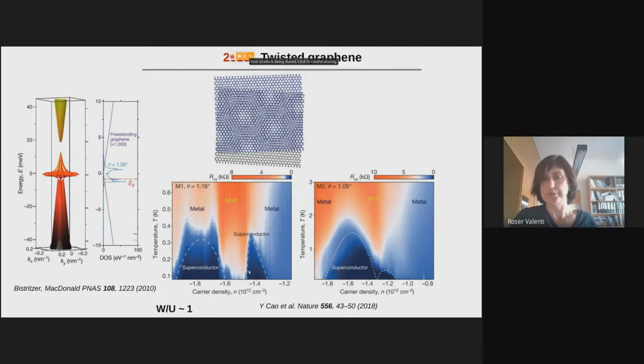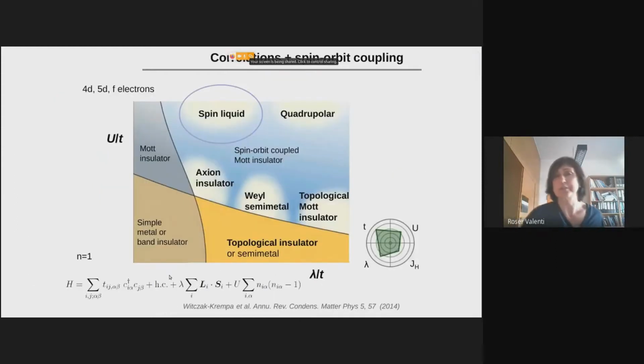So now let me bring the fourth interaction into the game, which is the spin-orbit coupling. And here, if we now include spin-orbit coupling and we consider systems where all these four interactions are playing a role, depending on the strength of the interaction, we can have even more phases in our systems. So here I'm showing basically the Coulomb repulsion as a function of the strength of the spin-orbit coupling. And as you can see, if I go to large Coulomb repulsion, we have these Mott insulators like the high-TC cuprates in the parent compounds. But then as a function of lambda, we have a large variety of new phases like spin liquid, axion insulator, Weyl semimetals, etc., etc.